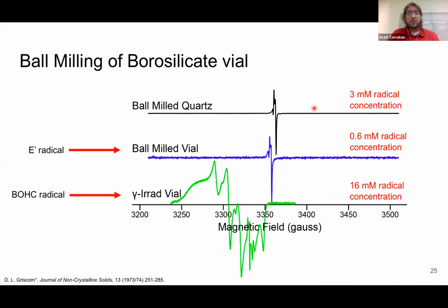I talked a little bit about the borosilicate vial. The gamma radiated vial gave this very broad spectrum, which is an oxygen-centered radical near a boron, a boron-oxygen hole-centered radical. What we saw when we ball milled it was a completely different type of radical, an oxygen vacancy radical. So by changing the method of introducing these radicals, we're able to make different radicals. As we can see, we got the exact same radical in the vial as in the ball milled quartz. We weren't able to get DNP on the gamma radiated vial.